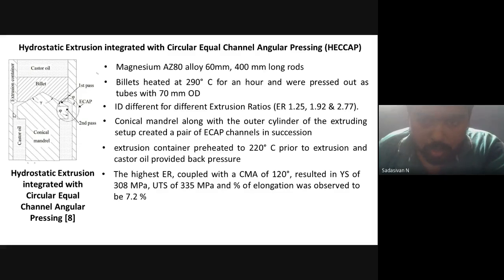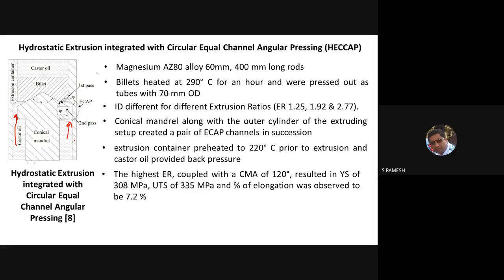The highest extrusion ratio produced good strength enhancement: 308 MPa of yield strength, 335 MPa of ultimate tensile strength, and a percentage elongation of 7.2, which is good for magnesium. It improved with the hydraulic back pressure that this castor oil is giving. Here, if you can see, this entire thing is filled with oil. There is some back pressure exerted, which is homogenizing the forming load.